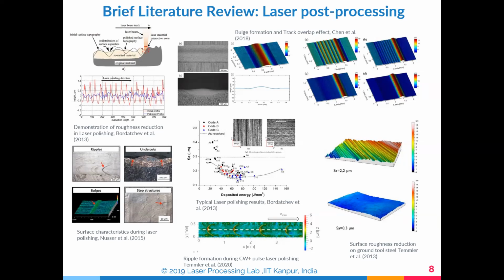peaks. Now what we are trying to do using a laser is either focus or defocus. When you defocus, the energy gets distributed in a plane. When the energy gets distributed in a plane, the flux intensity goes down. Once the flux intensity goes down, it will not melt and vaporize. It might go to a stage of melting and then depositing there itself, or it can deposit and then melt. So this is very important.